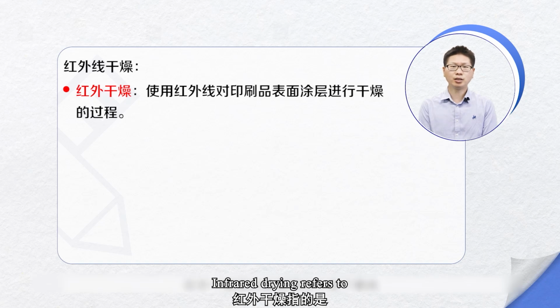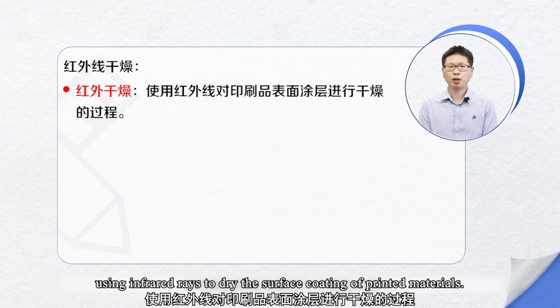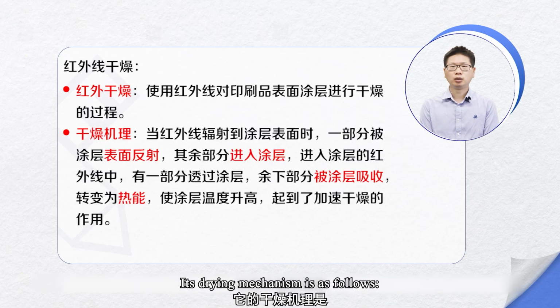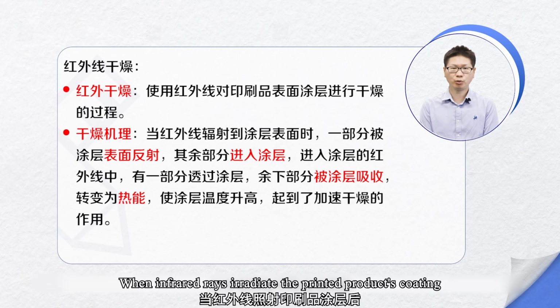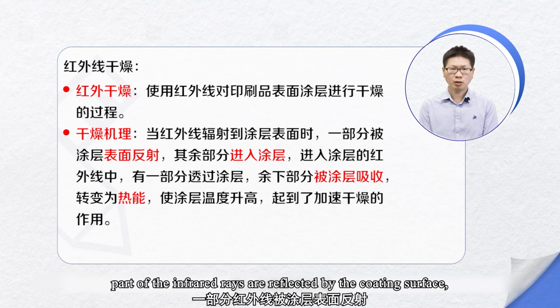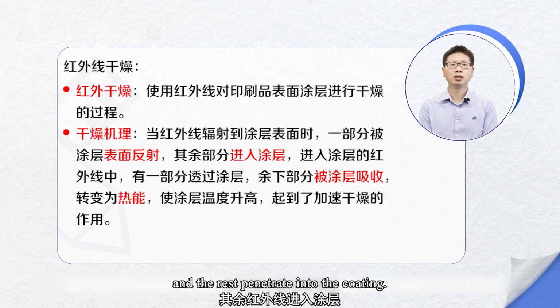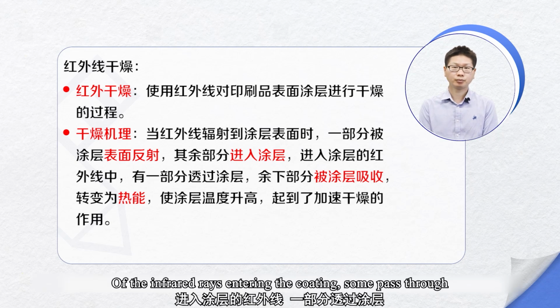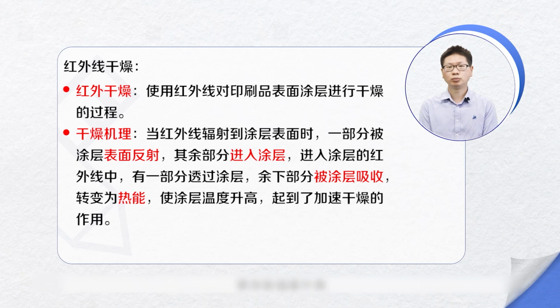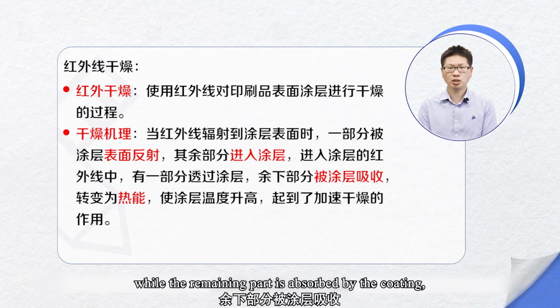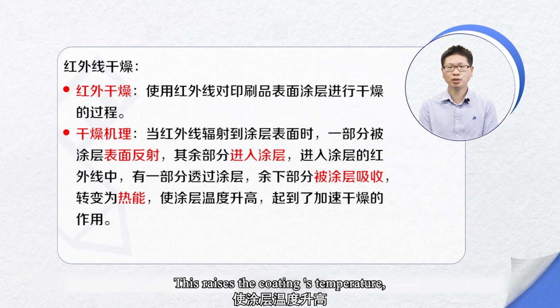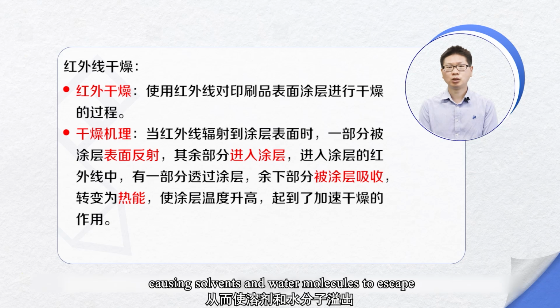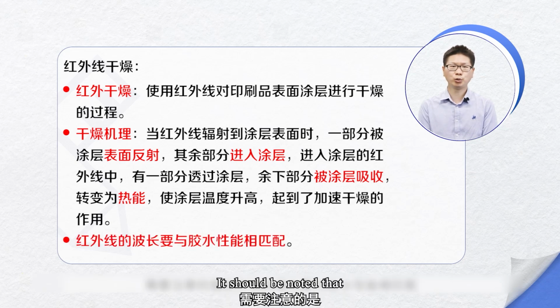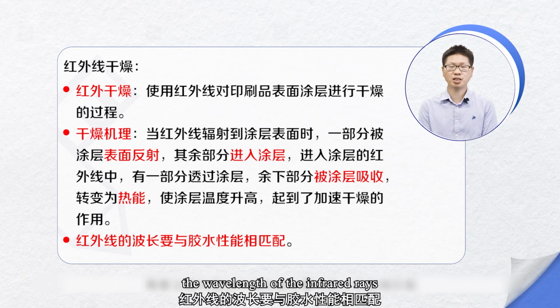Infrared drying refers to using infrared rays to dry the surface coating of printed materials. Its drying mechanism is as follows. When infrared rays irradiate the printed product's coating, part of the infrared rays are reflected by the coating surface, and the rest penetrate into the coating. Of the infrared rays entering the coating, some pass through, while the remaining part is absorbed by the coating, converting into heat energy. This raises the coating's temperature, causing solvents and water molecules to escape. It should be noted that the wavelength of the infrared rays must match the performance of the adhesive.